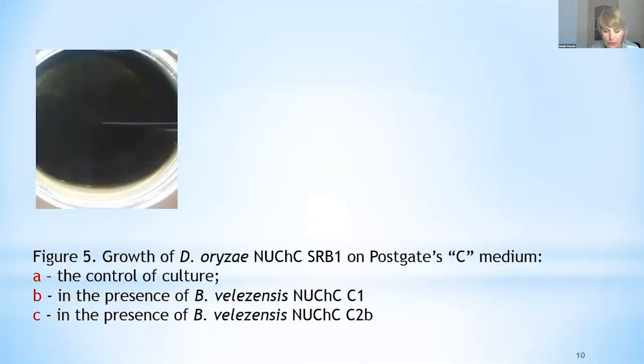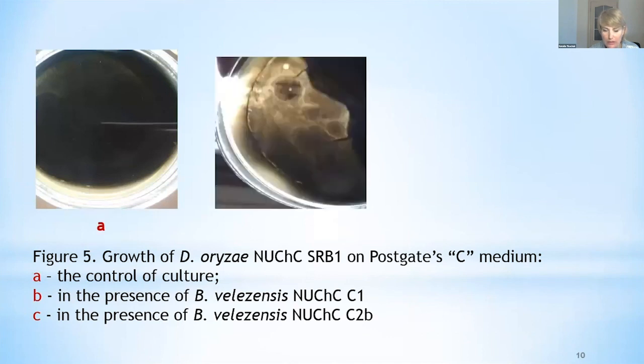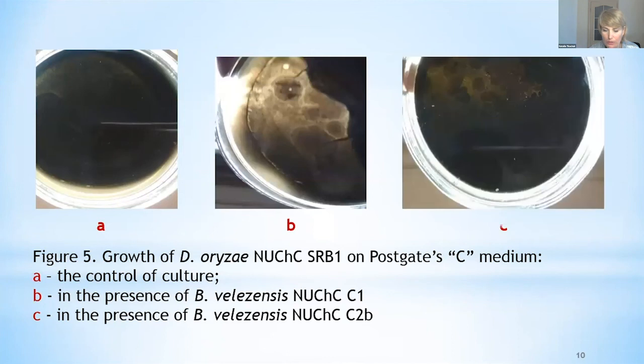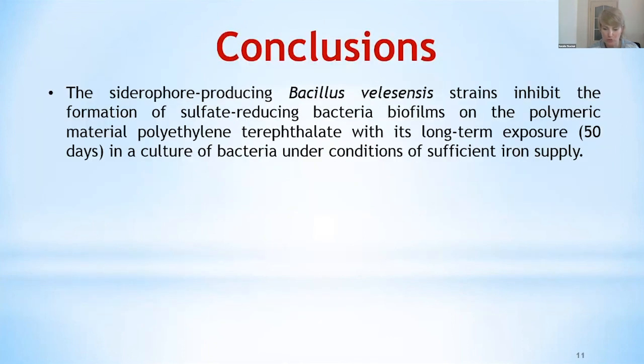Therefore, we further investigated the antagonistic properties of our Bacillus velezensis strains against sulfate-reducing bacteria, Desulfovibrio oryzae. It was found that sulfate-reducing bacteria Desulfovibrio oryzae develop around colonies of the strains. Sterile areas are absent. Therefore, the antagonistic properties of the studied Bacillus velezensis strains against sulfate-reducing bacteria were not observed. Thus, we can draw such conclusions.